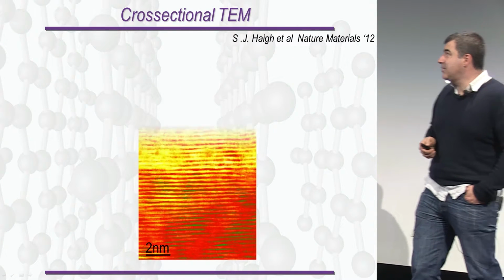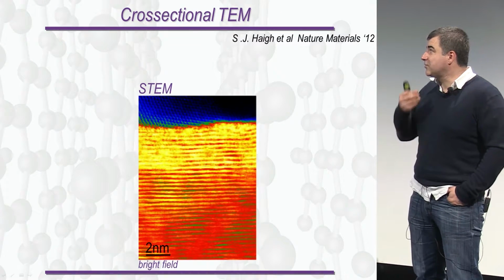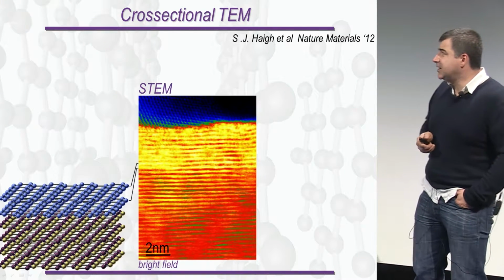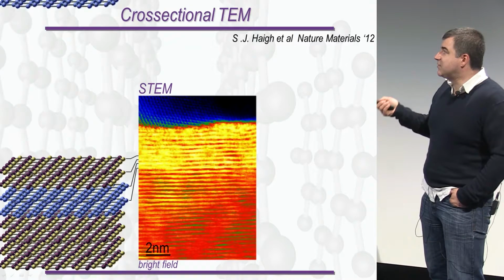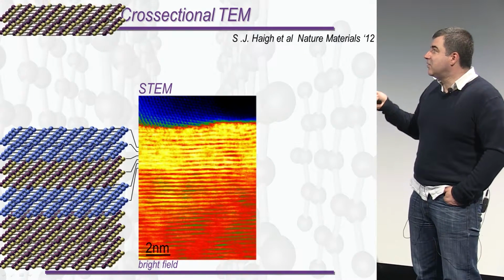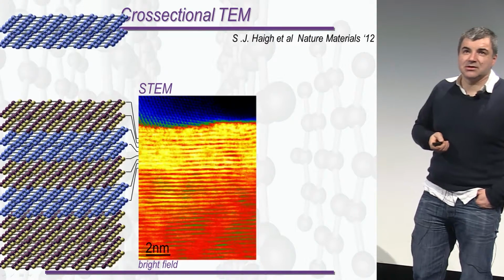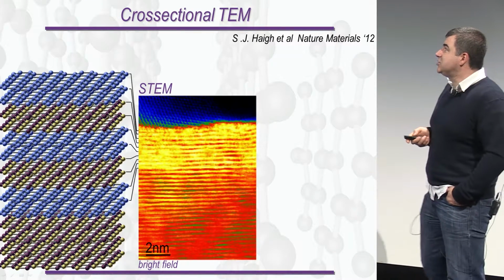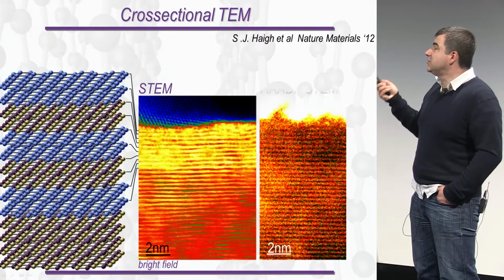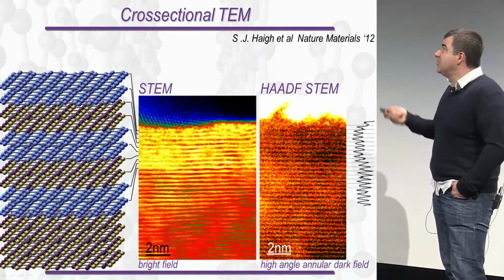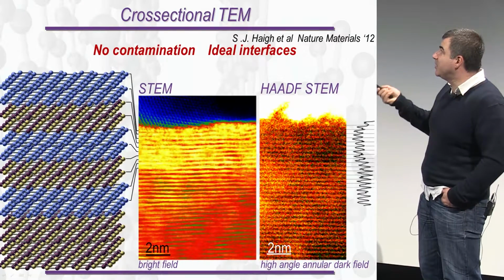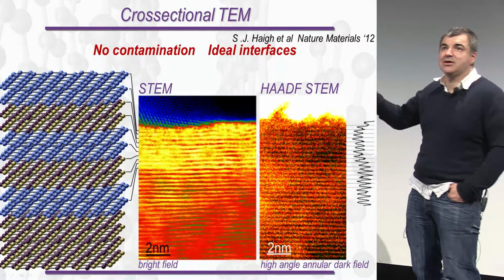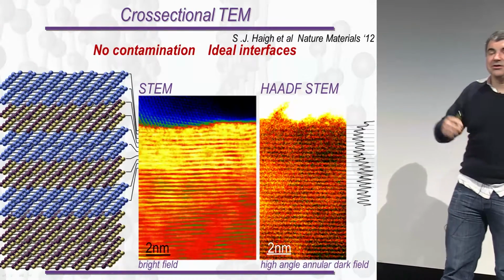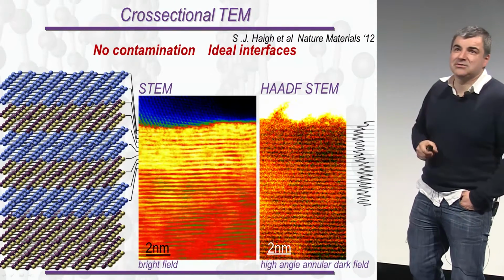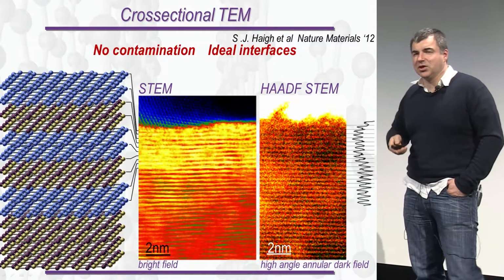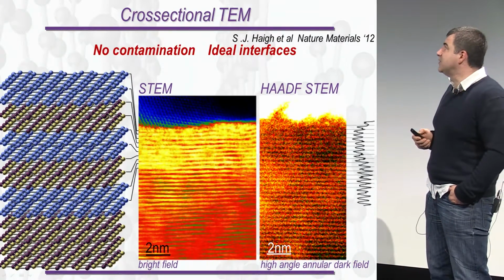Here is another example like this. It's also boron nitride together with bilayer graphene, and then there are several alternating layers of boron nitride and graphene on top of each other. And if I show you this dark field transmission electron microscopy image, then you probably won't be able to say where the bulk boron nitride stops and where graphene starts. So the quality of those heterostructures can be extremely good, and the electronic quality can be very good as well.